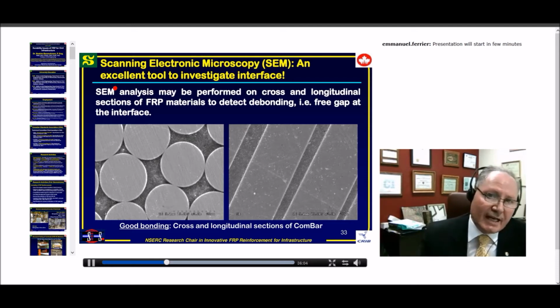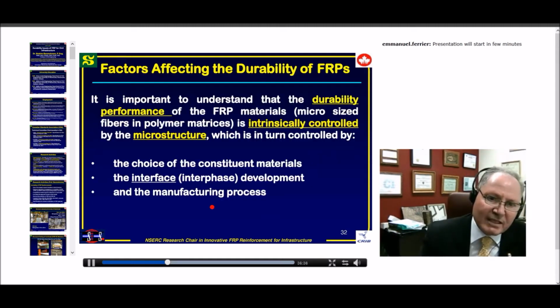Scanning electron microscopy is an excellent tool, as you know, to investigate the microstructure of this material, mainly looking at the interface. As you can see here, we have really good fibers and good distribution. This is a longitudinal section, and this is a cross section. This is very good bonding, and there is no gap or anything like that. And this is one of the bars, ComBAR, I think it's from Schöck, that I did this investigation on. I can come back to the manufacturing process.